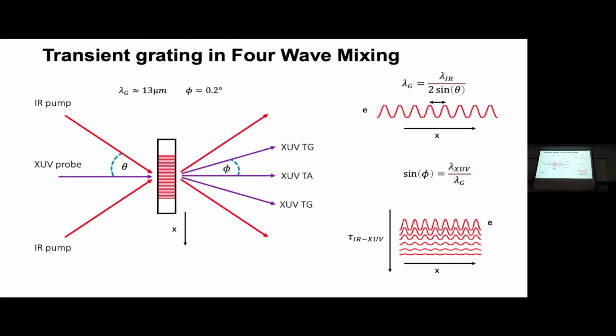So I write the grating, it's a carrier grating. So if I choose the right material, I can make electrons and holes. And the electrons and holes have a periodic modulation, and then I diffract off that. And in this material, there's a real and imaginary part of the dielectric function. So if you want to go back to your thing about your optics and so on, there's always a real and imaginary term, and the imaginary term gives us the absorption. But the real term we often neglect. It's responsible for the transient reflectivity and so on. And I want to show today we can get a lot of new information also out of the real term.